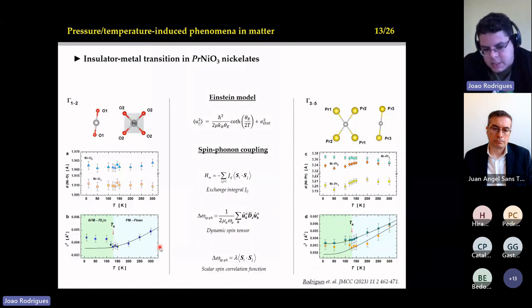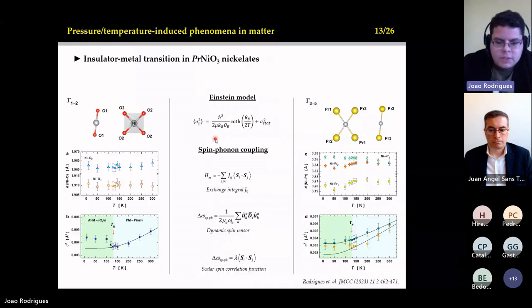So in some way, the spins start to be more correlated to the vibrations, because sigma square, or the u square, is somehow related to the vibrations of the bonds. So somehow there is a phonon coupling. We started thinking about a kind of spin-phonon coupling in this compound below the Néel temperature. Okay, so then we need to check what is happening with the exchange integral and then the dynamical tensor, which is a very technical detail, and you can see it in this paper here. But in the end, we have managed to quantify how much we have the departure from the Einstein model, which gives us an idea of how strong this spin-phonon coupling is.